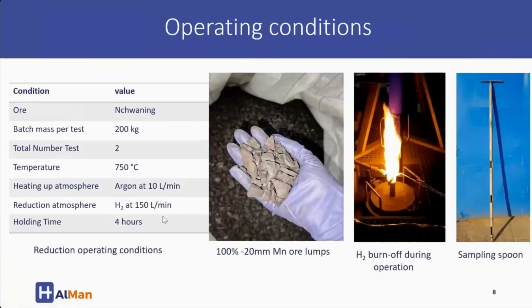We then went on to use 200 kg batches. We completed two tests for pre-reduction using 20 millimeter top size manganese ore lumps, with a target temperature of 750 degrees Celsius.